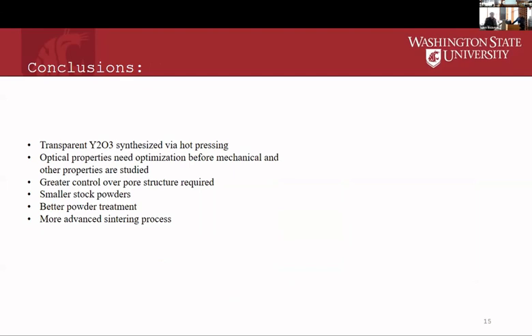Question: What were the two different density methods you used? So we have the water displacement method, where you submerge your sample in water—you can do alcohol or other solvents depending on what you're working with. We also had pycnometry, where you put your sample in a chamber, diffuse gas into that chamber, and determine the volume of your sample based on that. Then you divide the mass by the volume of the sample to achieve your density that way.